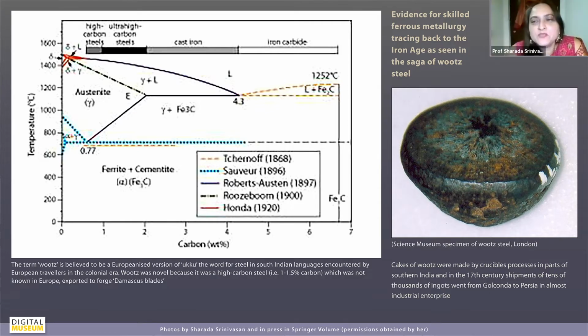Since we've talked about the bronze working, I just wanted to say that one can't see it in isolation because there is evidence for skilled ferrous metallurgy tracing back to the Iron Age as seen in the saga of wootz steel. Now, this term wootz is believed to be a Europeanized version of the word ukku for steel in South Indian languages, which was encountered by European travelers in the colonial era. Now, the novelty of wootz steel is because it is a high carbon steel with about 1 to 1.5% carbon, which was not really widely known in Europe. And it is thought to have been exported to forge these Damascus blades, which I'll explain.